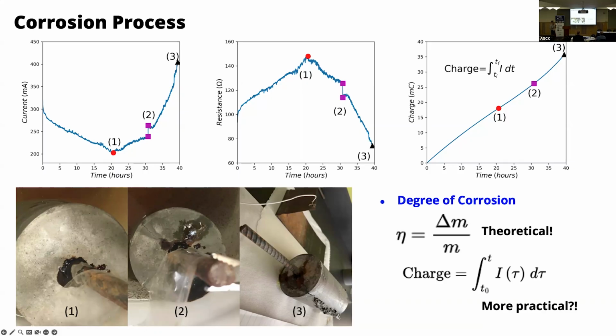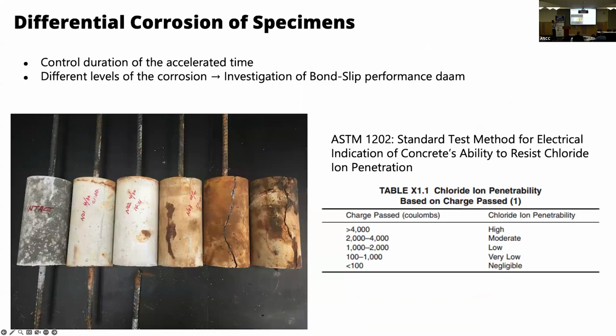Theoretically speaking, if you're going to define the degree of the corrosion, they use a mass loss. However, we cannot really measure the mass loss inside of the concrete. So instead, we just try to track down the charge by integrating the current with respect to time. Then we just try to use it as an indicator for the degree of the corrosion.